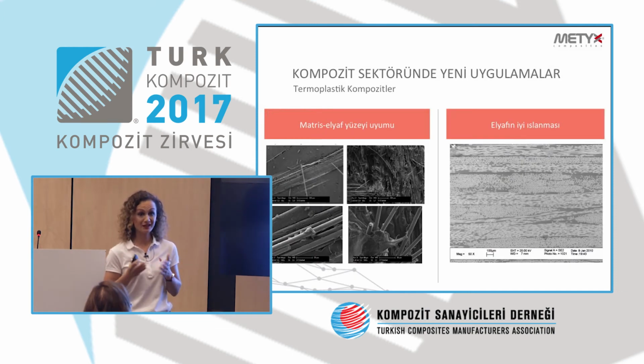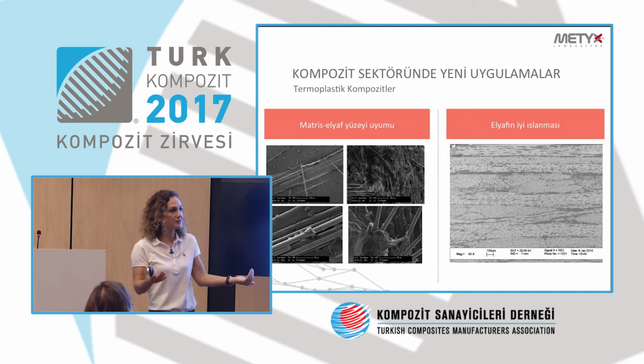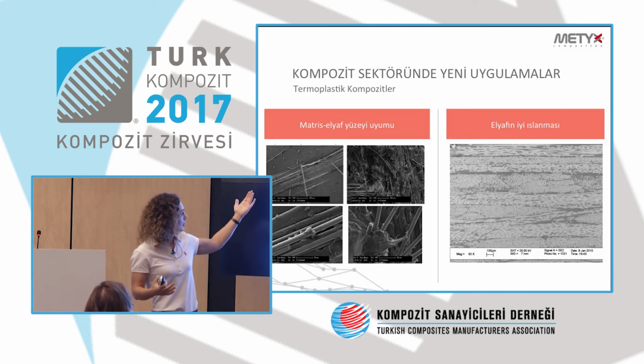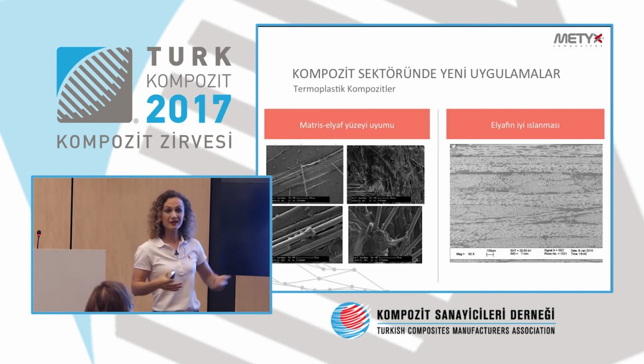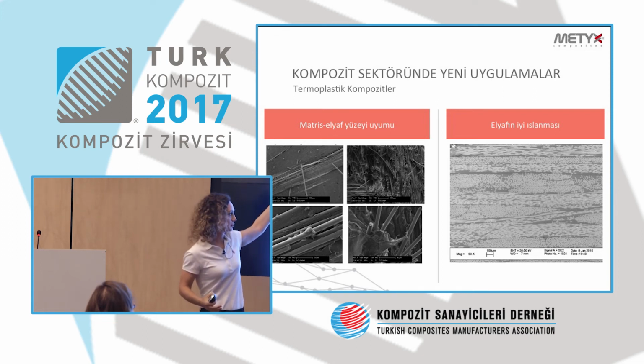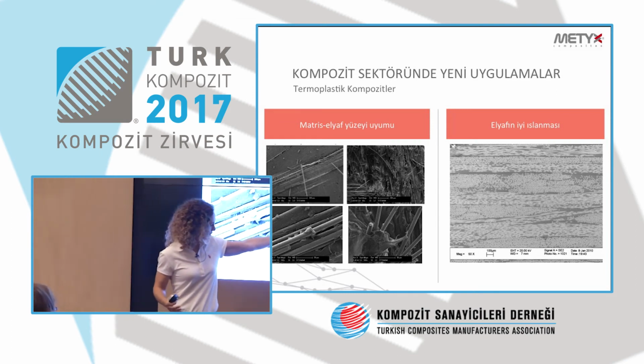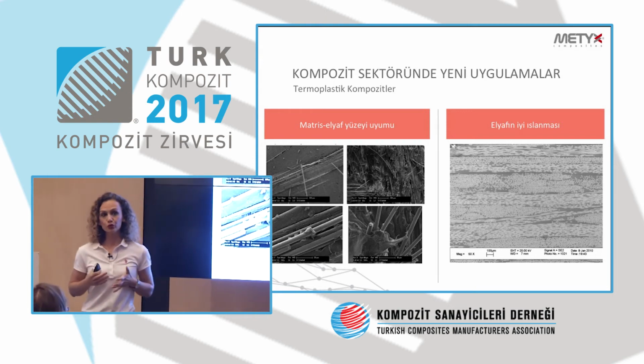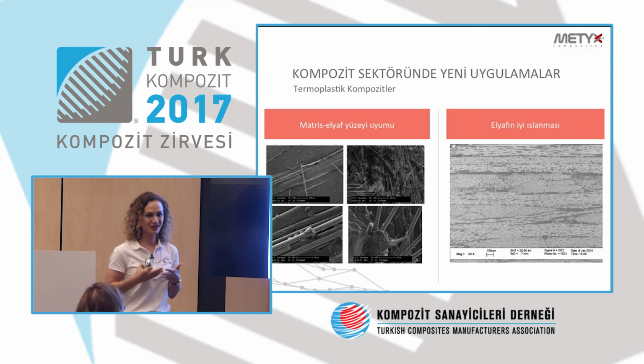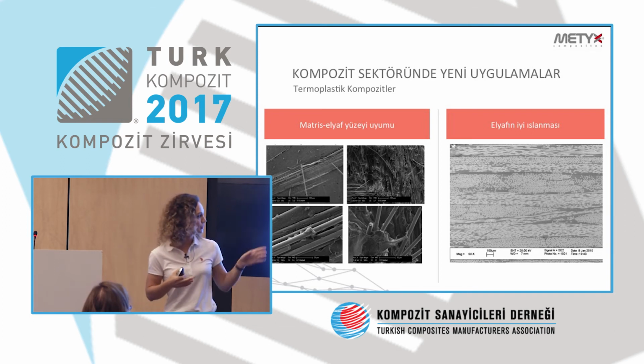So I told you before, the thing you need to pay attention to is whether the fibers have been dampened. How can we understand it? Let's say we have created a plate, but inside it the matrix and the fiber surface become very important, like in thermosets. The resins have to be quite proper with the material that has been used with them. Here the resin has not been bonded to the fiber, but here it has been wonderfully bonded. That is the reason why we need to find a fiber that is proper for the resin, and why we need to talk with the resin producer.